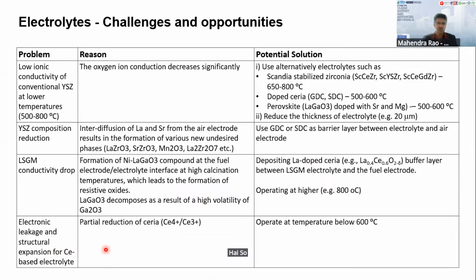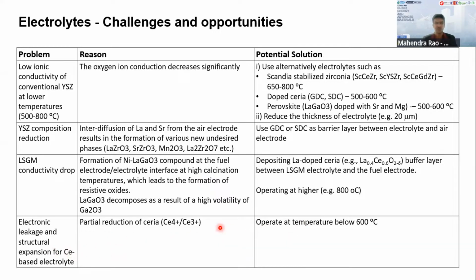So for ceria-based material, of course, we have some issues, especially the partial reduction of Ce4+ to Ce3+ when you operate at lower temperature, and then the partial oxygen issue. So this is another issue that we need to consider for ceria-based material, especially for Ceres Power. They are using ceria-based material for low temperature operation, so they have their own technology to mitigate all these issues.